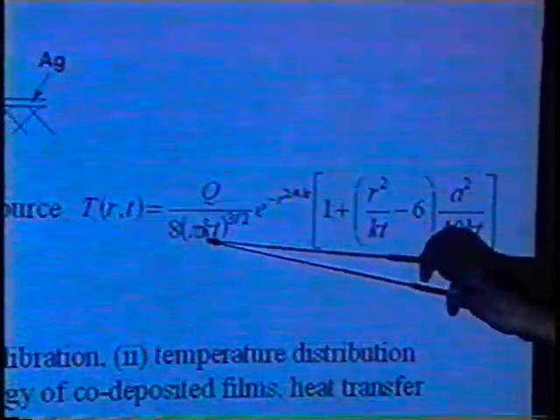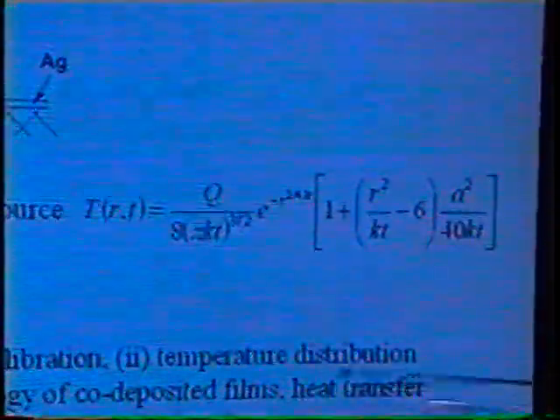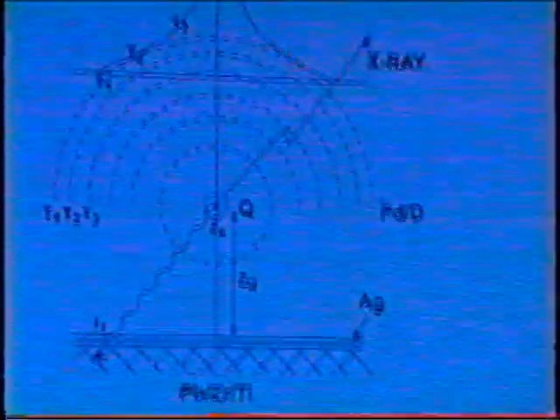And this is described by this equation shown here, where the temperature at any distance R and any time T is dependent upon the magnitude of the heat source. K here is the heat conductivity of the palladium deuterium material. A, of course, is the radius of the initial sphere. And if you take as a limiting case A goes to 0, in which case it's a point source, this equation reduces down to this form here. Now, actual quantitative evaluation is going to be very difficult. You have to do a transducer calibration.